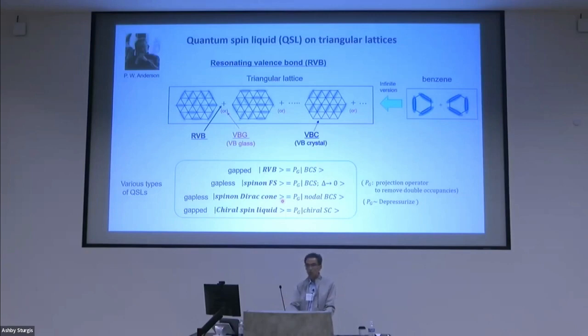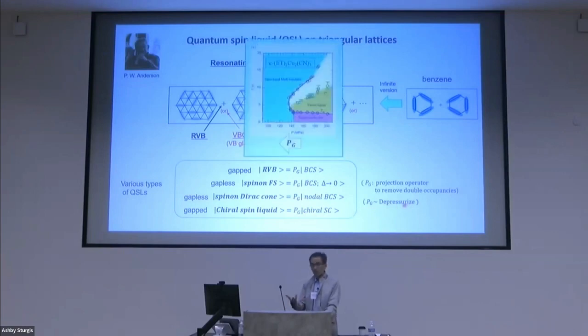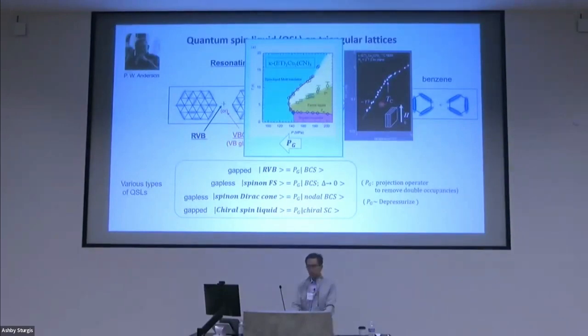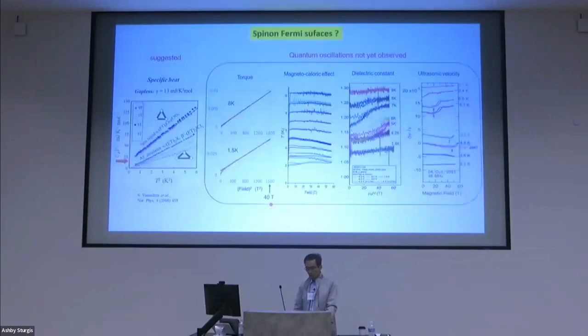Let me quickly flash the present status. Okay, first one is the spin liquid. The symmetry of the spin liquid is closely related to the superconductivity with the same symmetries through Gutzwiller projection operators, which remove the double occupancies. And the transition by pressure is sort of the experimental realization of the Gutzwiller projection operators. So superconductivity is here, and the NMR experiments suggest that the gap of this superconductivity is nodal. So from this we can get that the spin liquid is a spinon Dirac cone. However, the situation is not so simple.